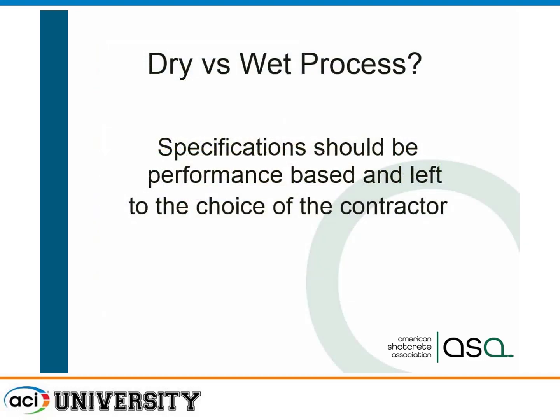I get a lot of questions. Well, which one's better, dry mix or wet mix? And really, both done properly with the proper material mixtures, placement, and equipment will perform equally. Dry mix is not more porous than wet mix. Wet mix tends to have a little bit higher water cement ratio because we have to pump it through that pump and through a fairly small hose, right? So actually, dry mix tends to be a little bit stronger, a little bit lower water cement ratio.